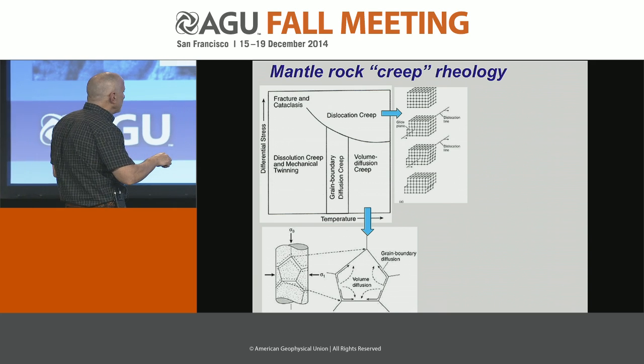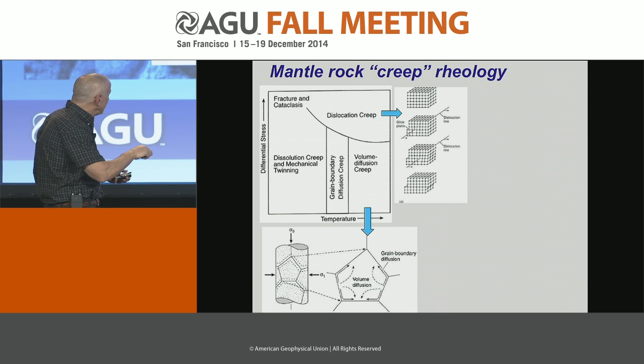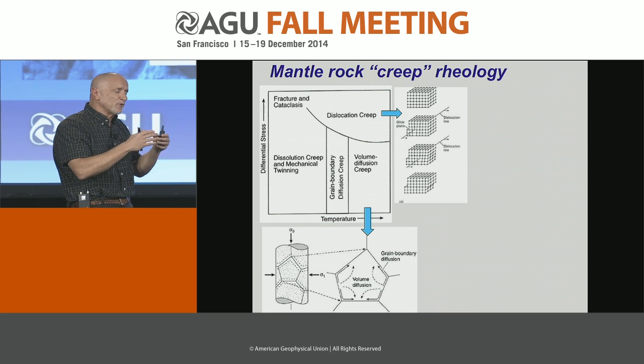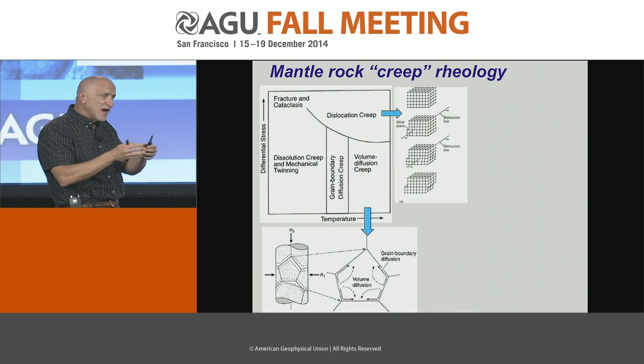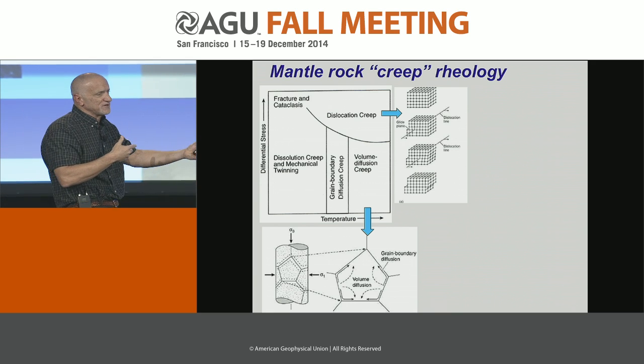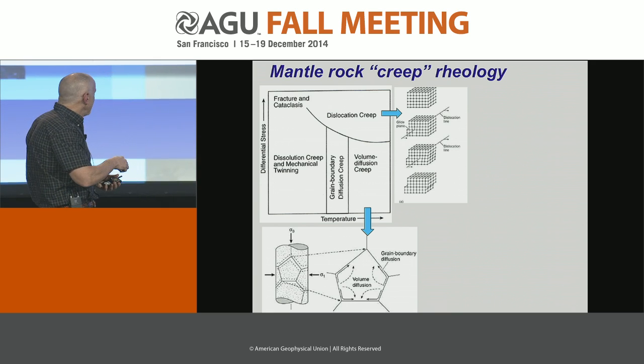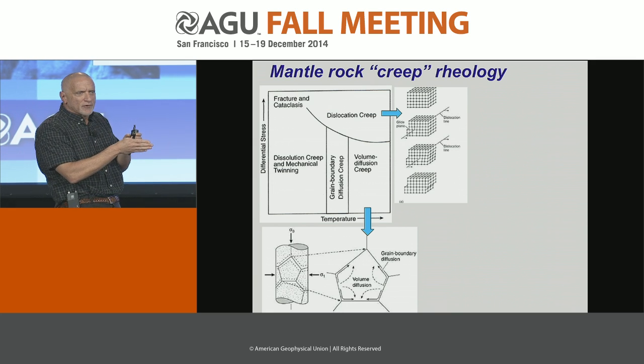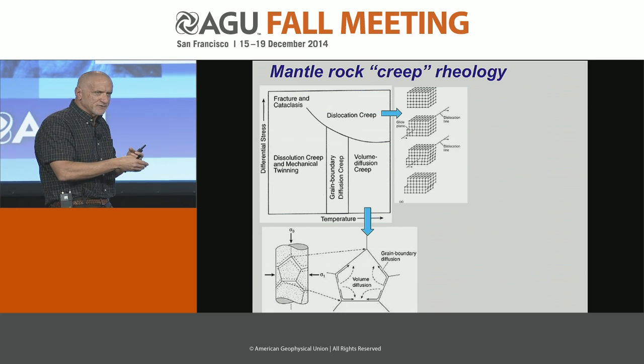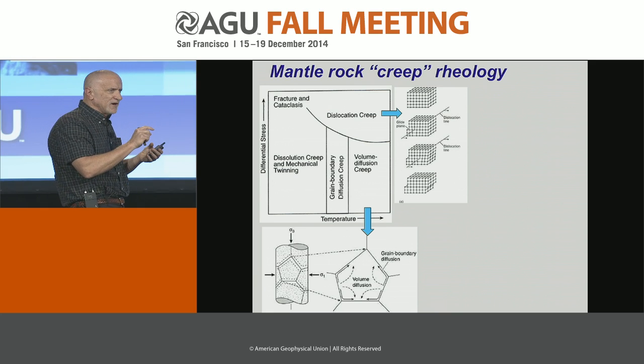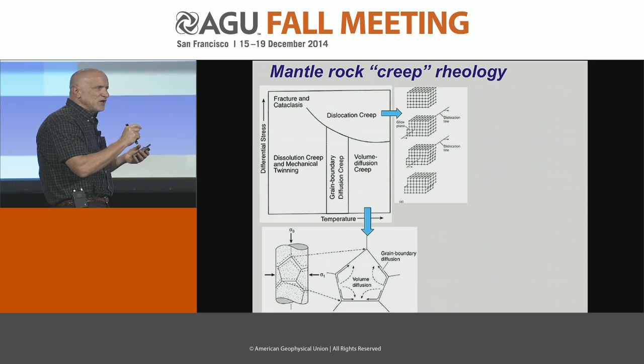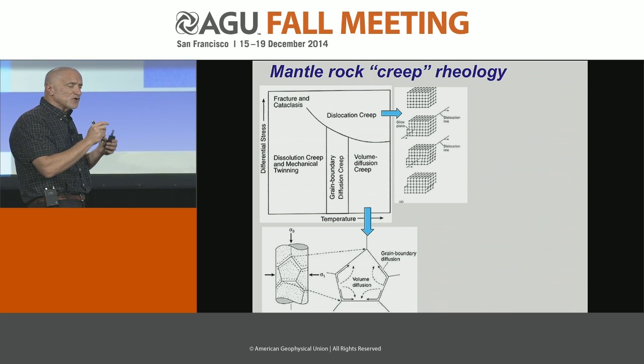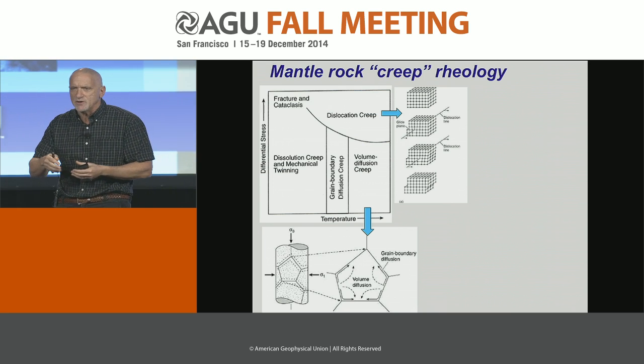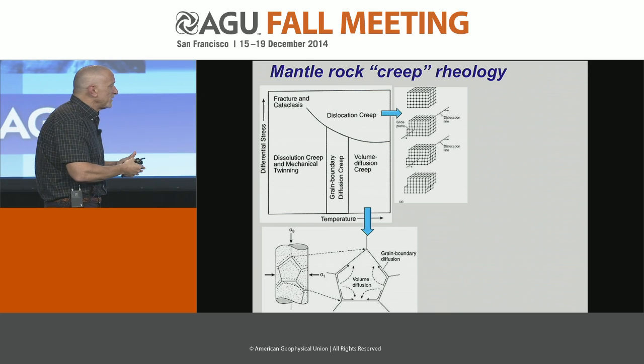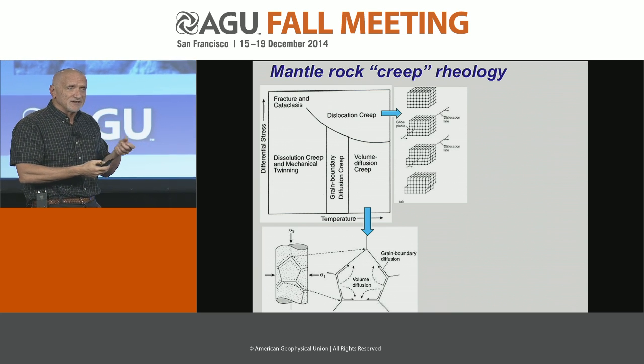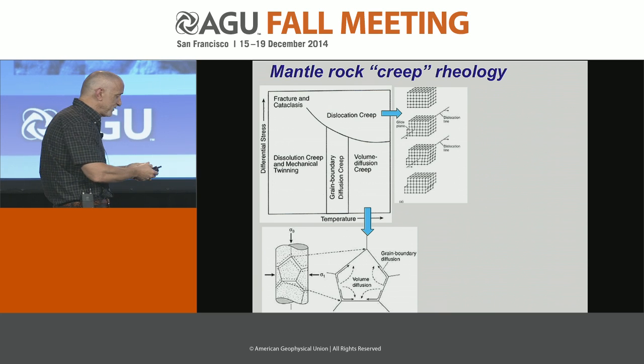It's at slightly lower stresses, ostensibly, but in which, as you're squeezing something, you're forcing atoms to diffuse away from where you're compressing it towards tension, relieving stress. The diffusion occurs either through grains or along grain boundaries, which means that if you have small grains, you have smaller grains to diffuse across, or many more grain boundaries and pathways that you can move through. So that implies that the smaller the grains are, the easier it is to drive this diffusion.